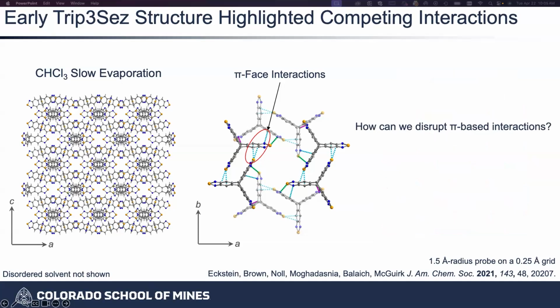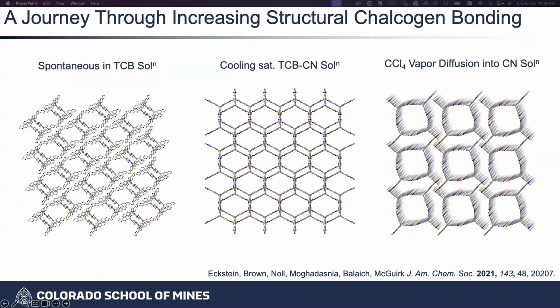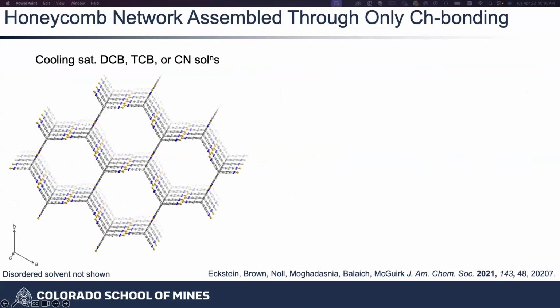You have to take information from structures, even if you don't think it's anything that you wanted. I think that's so important. And so we went and actually took these chloroaromatic solvents that are well known to break up pi-based interactions and started growing crystals out of those. And we went on this journey where we were able to get all these different structures, basically increasing the effective porosity of the system and decreasing the density, while also increasing the amount of those contacts between selenium and nitrogen. And eventually, we were able to get to exactly the structure that we wanted.